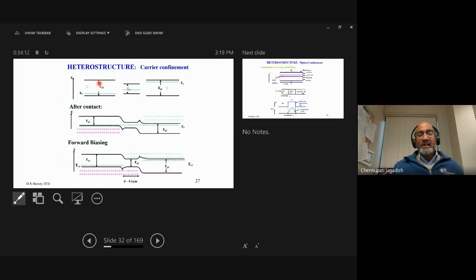Here is a case of a heterostructure, with a larger band gap material and, on both ends, a smaller band gap material. If you bring them together, the Fermi level alignment takes place, and you can see that the holes are here in the p-type region and the electrons are here. Now you can forward bias these. Again you create the quasi-Fermi levels, and electrons are injected into the smaller band gap region, and holes are injected here. Because of this barrier height, electrons cannot go that way and holes cannot go this way. That means you create a barrier for electrons and holes, and that's where they end up recombining very efficiently.